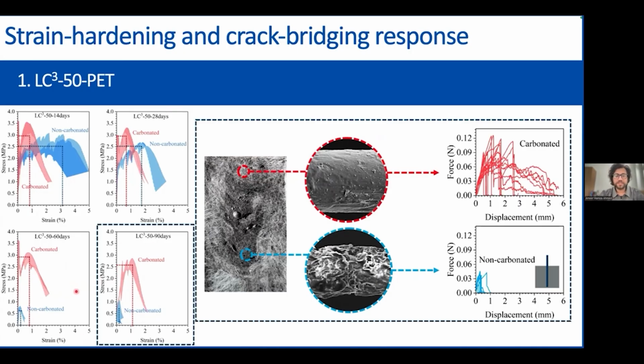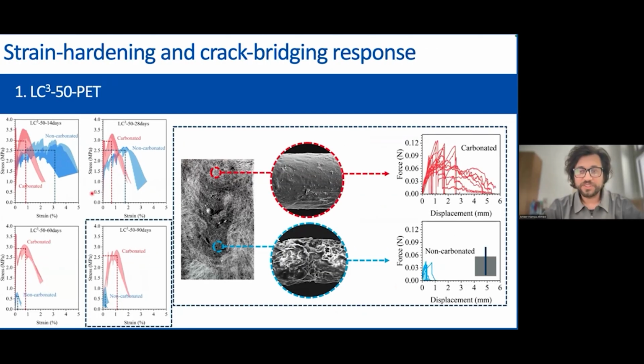leading to such worsening of the tensile properties. In contrast, when we look at the red envelopes, we can clearly see that carbonation allowed these composites to retain their tensile performance across all ages. So across all these four ages, we can see how the tensile performance was preserved. It's basically because the alkalinity is reduced quite significantly, which is beneficial for mitigating the alkaline degradation of PET fibers. However, the tensile strain hardening behavior is not so prominent or desirable here, because there's not so much multiple cracking and not so much ductility arising even after carbonation.